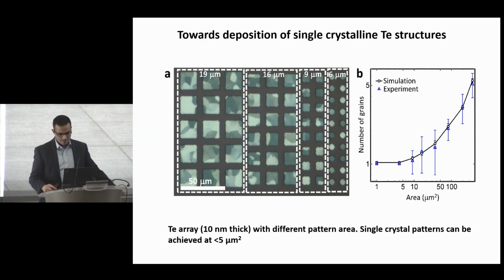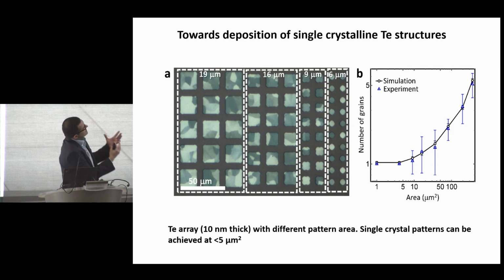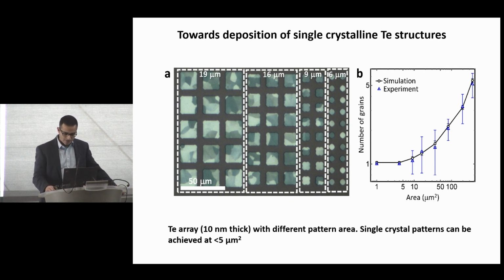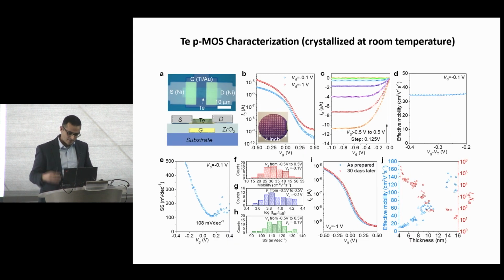And the grain sizes are on the order of tens of microns for a material that is crystallized at room temperature. And of course, you can do some structural engineering. You can template it. So if we template the evaporated tellurium into smaller patterns, then we can get single crystals at each pattern. And so this is a mechanism by which you can form single crystalline arrays of tellurium structures on your oxide, all processed at room temperature. We have built different types of devices using tellurium.